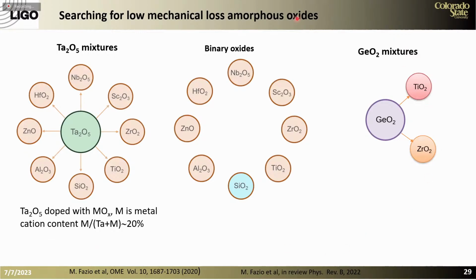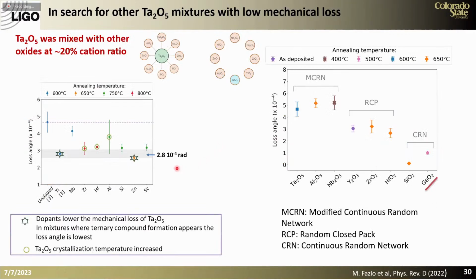Okay, so we studied a bunch of materials to understand how we can actually reduce mechanical loss. We studied tantala mixtures, binary oxides, and the germania mixtures. And what we learned is that in the tantala, when it was mixed with other oxides, we obtained the lowest mechanical loss when we use titania, which is what LIGO has been using, and zinc. When we looked at the binaries, we confirmed that silica and germania, which are continuous random network glasses, achieve the lowest loss angle.